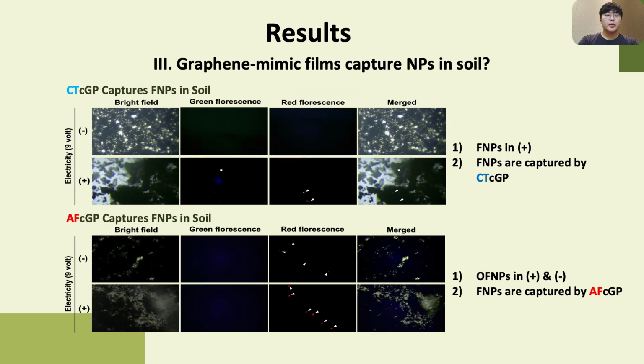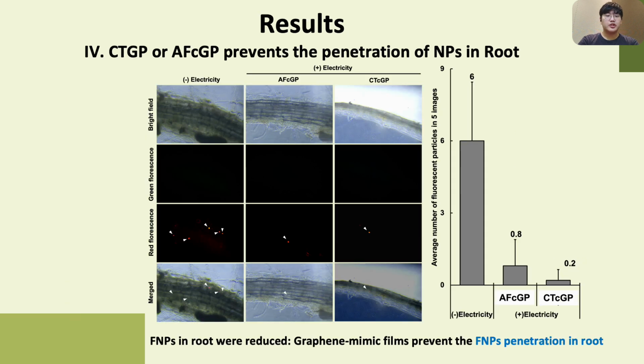Third, I determined whether the nanoplastics in the soil could be captured by the graphene mimicking film supplied with electricity. As a result of observing the film surface under the fluorescence microscope, I could detect many nanoplastic particles on the surface of both films, CTCGP and AFCGP. It indicates that CTCGP and AFCGP can effectively capture nanoplastics. Finally, I investigated whether the electrically supplied film could suppress the penetration of nanoplastics into crops. The number of nanoplastics in the roots was significantly reduced by the CTCGP and AFCGP supplied with electricity. Therefore, I showed that the film can effectively prevent nanoplastic penetration into crops.